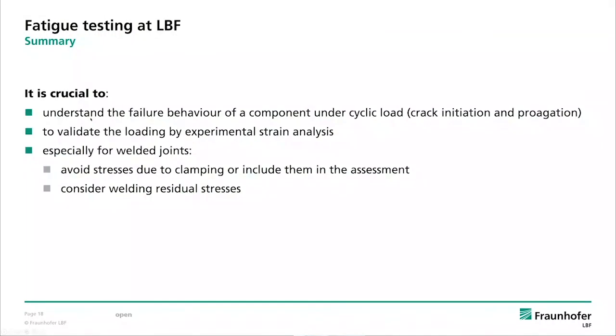So it's crucial to understand the failure behavior of components under cyclic loads, to validate the loading by experimental strain analysis, and especially for welded joints, to avoid the stresses due to clamping, or at least to include them in the assessment, and to consider welding residual stresses.